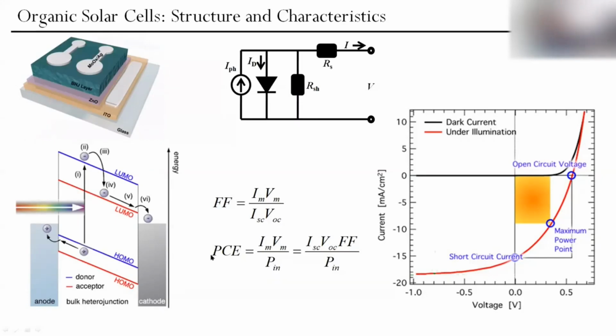So the performance of solar cells, which is called photo conversion efficiency and is considered to be the most practical and important parameter of solar cells, is the ratio of maximum output power to the input power, which is like the power of sunlight per square meter, or per active area of the solar cell, because it can be a different area, which we apply to the solar cell. And that's why it's the product of short circuit current, open circuit voltage, fill factor, divided by this input optical power, which we shine on the solar cell.